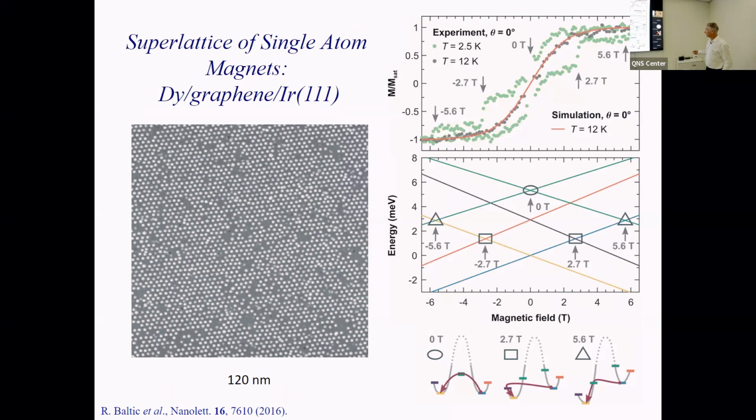So these are curves that we can record on a sample where we deposit the atoms at very low temperatures where they cannot diffuse at all, and at samples where they form this nice superlattice. So this means they don't have to be 2.5 nanometers apart. They can be very close even. So we have calculated that, for example, holmium needs an external field of 8 Tesla and it doesn't switch. So you would have to apply even bigger fields. So you have to be pretty close between two atoms to have a stray field of one atom that has 8 Tesla that acts on the neighboring atom.